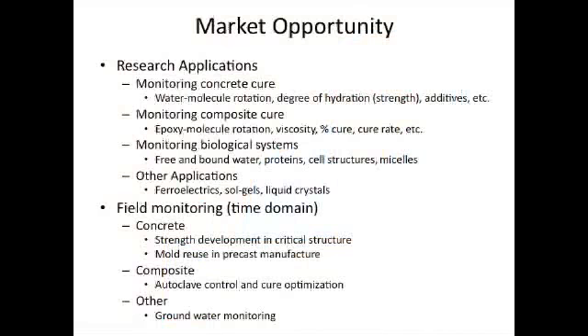The applications and market opportunity — one we've worked on considerably is monitoring concrete cure. The small molecule acting in concrete cure is the water molecule combining with calcium and silicate to form the hydrate, which is the hard material all around us. We're able to provide information on the degree to which that reaction has taken place — degree of hydration, which relates to strength, and the effect of additives on the concrete cure.